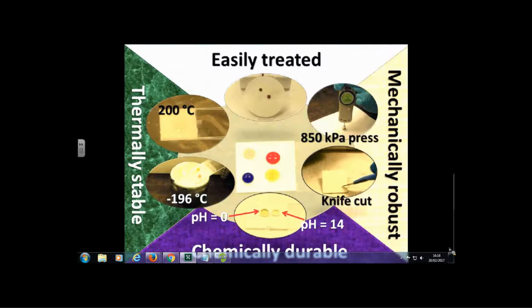These coatings are easy to apply and very mechanically robust, so you can put them under high pressure and they will still function. You can cut them with a knife and they tend to self-heal and still function as slip surfaces. You can cool them down to liquid nitrogen temperature and then warm them up to room temperature and they still work.